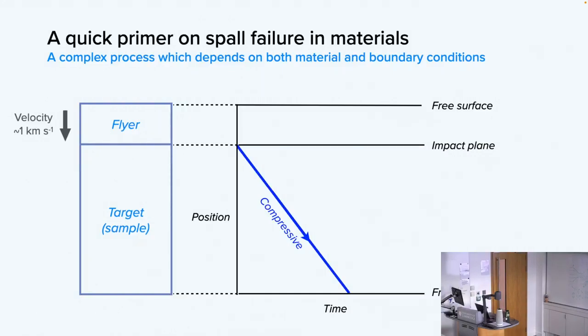When that compressive wave gets to that free surface, it reflects off the free surface because, of course, there's a difference in impedance between the solid material and the air that's behind it. And when it reflects, it actually reflects back as a tensile wave. So now I have a tensile wave, which is propagating back in toward the interior of my target.